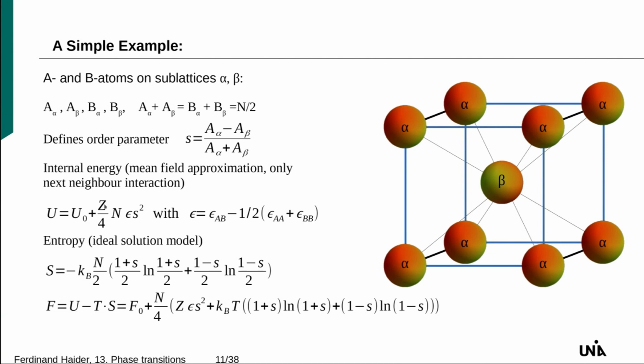That is, as before, the number of next neighbors, 8 in this lattice, N is the total number of atoms. Epsilon is what we call the pair exchange energy, the difference in energy between an AB pair and an AA plus BB pair. If this is positive, this means the energy of an AB pair is higher than AA-BB pairs, which would mean we go into a precipitating system. If it is negative, that means AB pairs are favored, and then we have what we want.